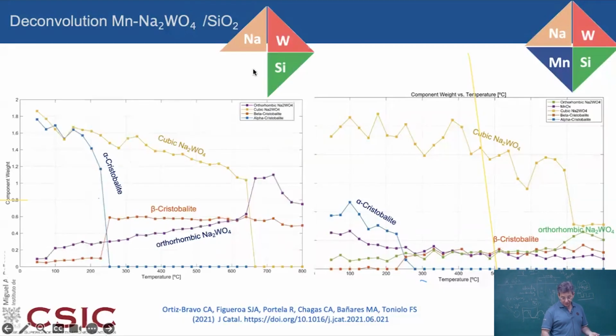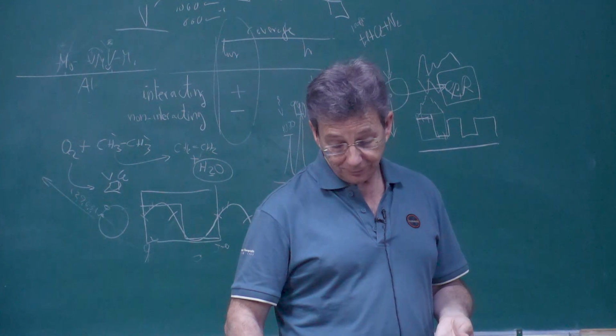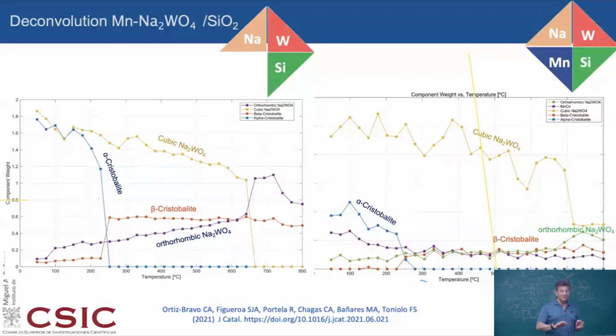Here, for instance, you have on the left without and on the right with manganese. Things may look alike, but you can see the moment at which the cubic sodium tungstate decreases compared to the dominance of the orthorhombic one. So relative populations are changing, and this is also associated with a better performance of the catalyst. Actually, the manganese promoted sodium tungstate on silica is much better than the one without manganese. But whatever, for today, this is it. We still have 10 minutes for questions, and tomorrow we will continue.